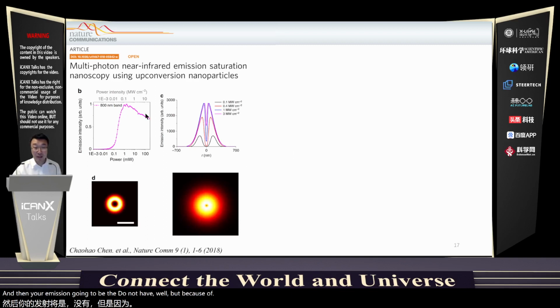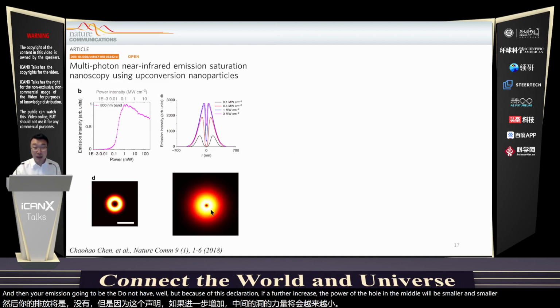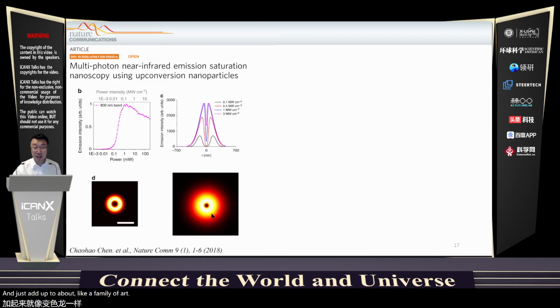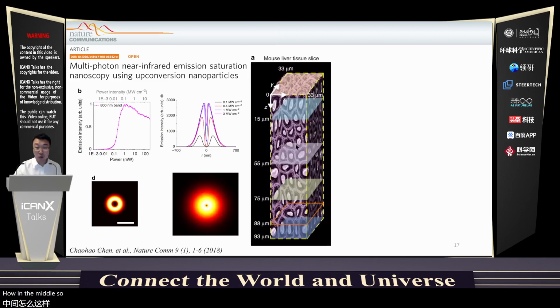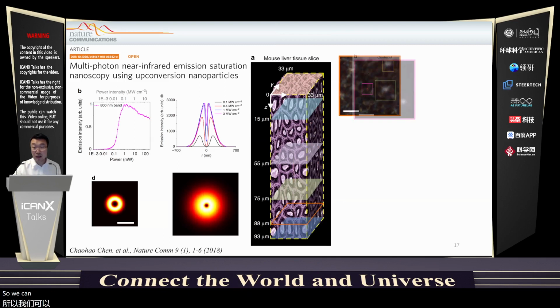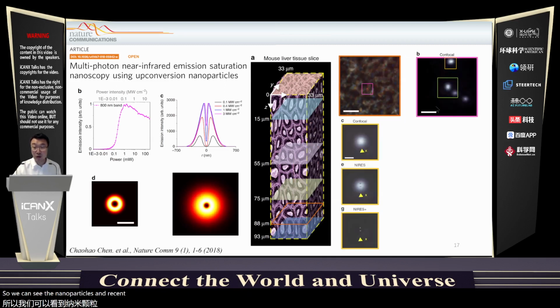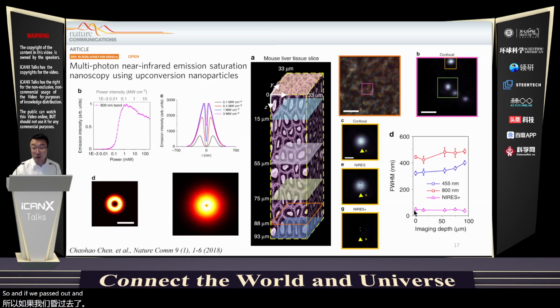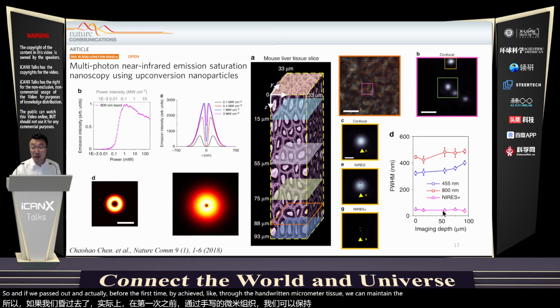But because of this saturation, if we further increase the power, the hole in the middle becomes smaller and smaller. At about 10 milliwatts, the hole goes beyond the diffraction limit, so you have a tiny hole in the middle. We used this technology to watch nanoparticles through deep tissue, 100 micrometers. With confocal, you see one particle, but if we turn on the super-resolution, it's actually 2 nanoparticles. For the first time, through 100 micrometers of tissue, we can maintain 50 nanometer resolution.